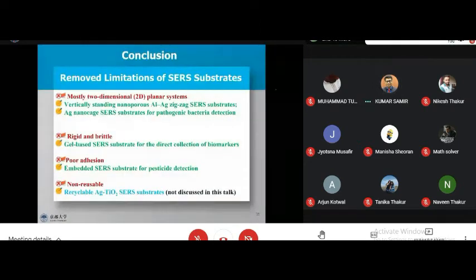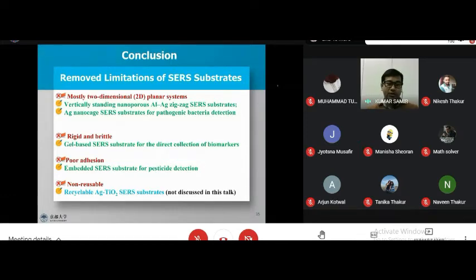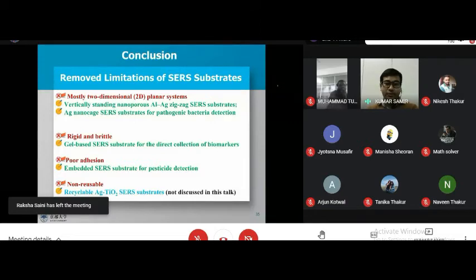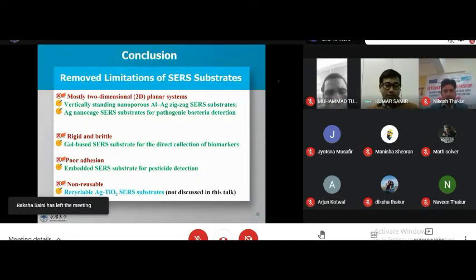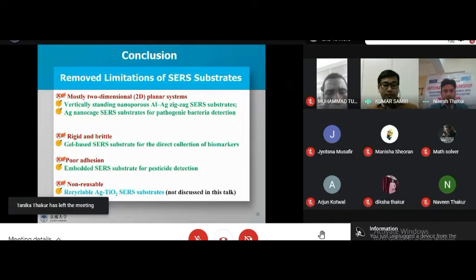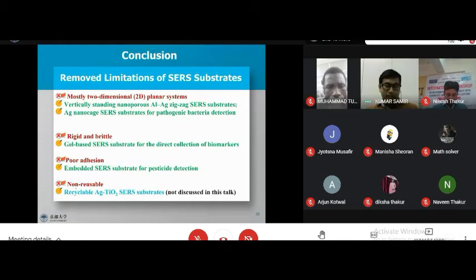So in conclusion, we have removed the limitations of SERS substrates. Since they are mostly 2D planar substrates, we fabricated two types of SERS substrate, vertical zigzag and the wrinkle type structure, to remove this limitation. We removed the rigidity and brittleness by producing gel-based SERS substrates and by embedding them into the polymer. We also removed the poor adhesion by embedding it inside the PDMS. I have also fabricated a recyclable silver TiO2 SERS substrate, but not discussed in this talk.